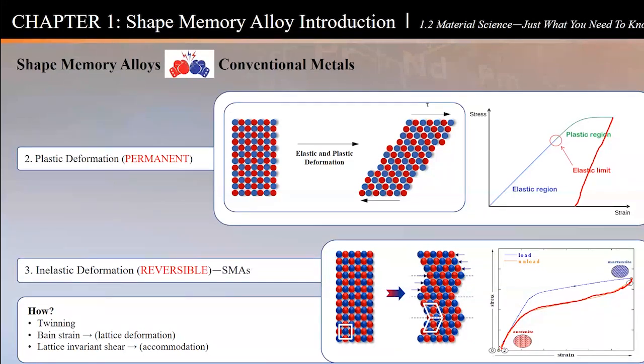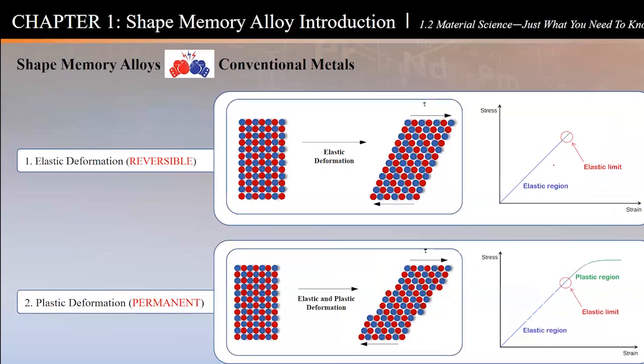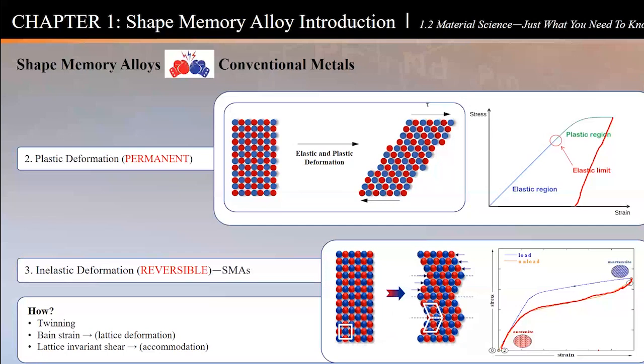So if you have a conventional metal, aluminum, what have you, you can deform it to 0.6%. 0.6% is what's all reversible. This shape memory alloy here, you can deform it 10 times that. That's 6% fully reversible strain. And that's the power of shape memory alloys. So keep in mind this principle again. This is reversible, and it is enabled via a phase transformation from a higher symmetry parent austenite phase to a lower symmetry martensite phase. That's how this happens. Here's a quick picture for you. So again, remember these little twins that you see here.